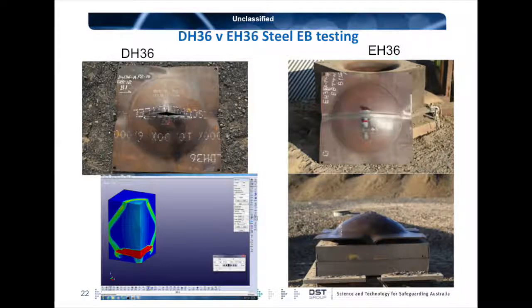So just to show you some of those results, for instance, the DH36 steel versus the EH36 steel. Basically that's 360 megapascal yield, typical ship hull plating steel. In one of those explosive bulge tests where they crack or weld a crack arrest starter here, as those plates deform, the DH grade, which I guess is a lesser grade than the EH grade, begins to split, but the EH grade steel stays intact.